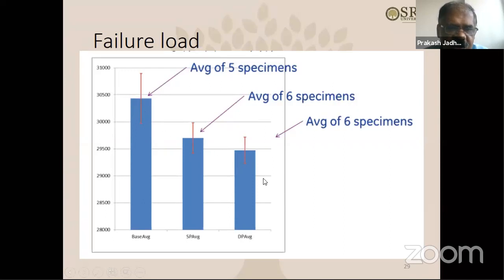Of course the failure load is different, but this is the final ultimate failure load. What we were interested in was the initiation failure load, and that was very difficult to obtain, but we were able to obtain it using the acoustic emission and also DIC. Why are we interested in the initiation failure load? Because the ultimate failure load is not the real indicator of failure. You can't really depend on ultimate failure when it's happening.